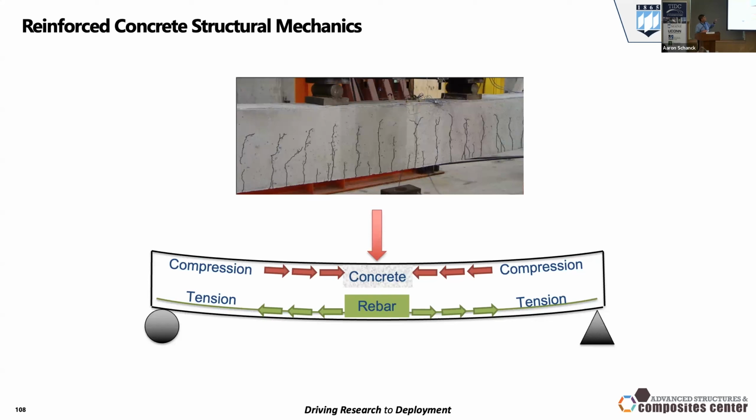Now, the way beams work in concrete is the concrete cracks, and that's not bad, okay? We are exaggerating the cracks because we penciled them with a Sharpie and went to larger deflections, but a good, well-designed reinforced concrete beam will have a nice cracking pattern, not really very visible, with very small cracks, so we don't want chemicals and water to get to the reinforcement. But the question is how to make these two materials work together through good bond between the tension reinforcement and the concrete, okay? How that can happen.